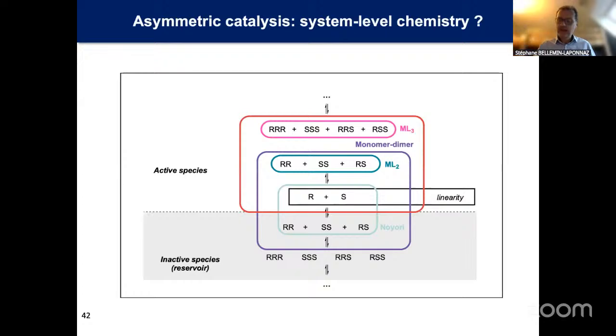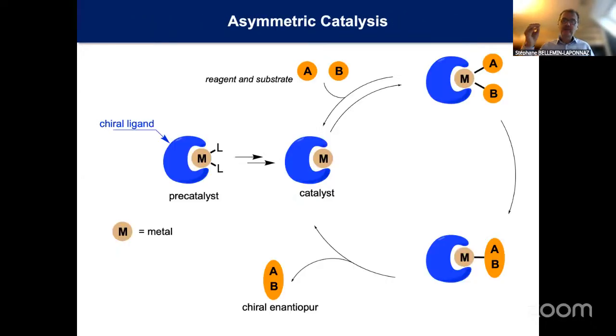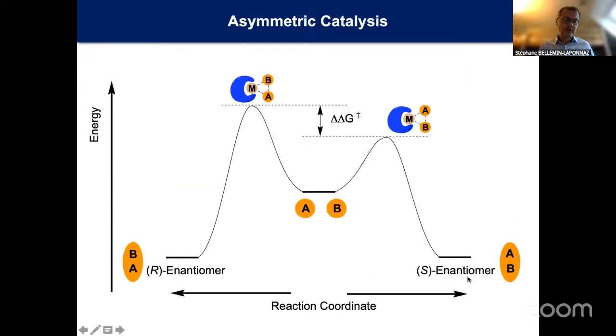So in conclusion, if you think about asymmetric catalysis, the way we are thinking about catalysis should be seen more like a system-level chemistry where you have competition between different active species. This means that when you want to design a catalyst and design an asymmetric reaction, the way we are thinking to do that is designing a ligand using a metal, and then you draw this very simple catalytic cycle where you have the reagent and give the product. That's the way we are designing catalysts. The goal when you want to get selectivity is to play with the possibility to generate the two enantiomers, and as soon as you have a large delta G between the two transition states that give the two enantiomers, then you can have selectivity.